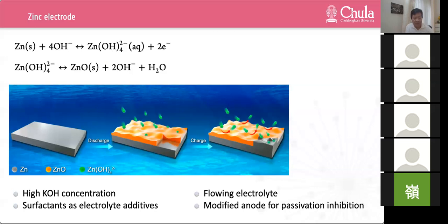In contrast, the positively charged polar group of CTAB shows weak interaction of zinc ions, leading to generation of larger zinc oxide particles. In addition, surfactants with multiple anchoring groups have advantages in binding the anode surface to inhibit the formation of zinc oxide passivation layer. In addition, for zinc air flow battery, the convection condition of the electrolyte also have an impact on the physical chemical property of the zinc passivation film. A flowing electrolyte reduce the effects of a passivation layer by removing loosely deposited passivation layer and reducing local concentration gradients.